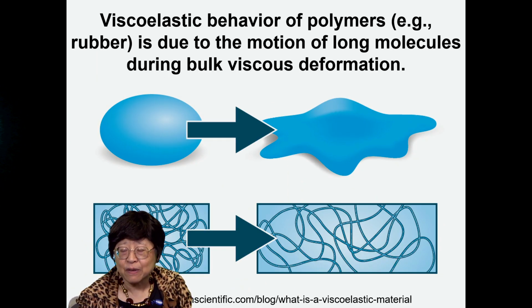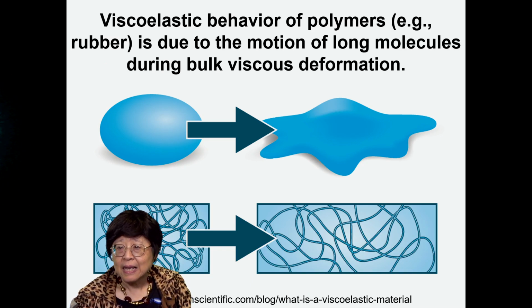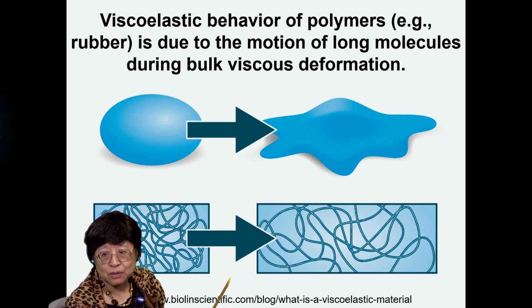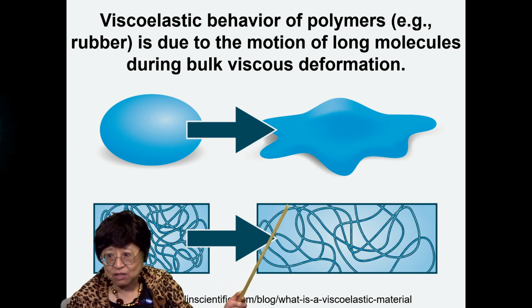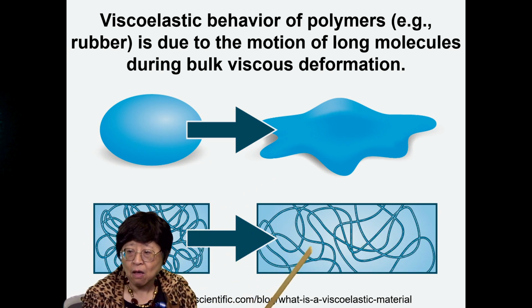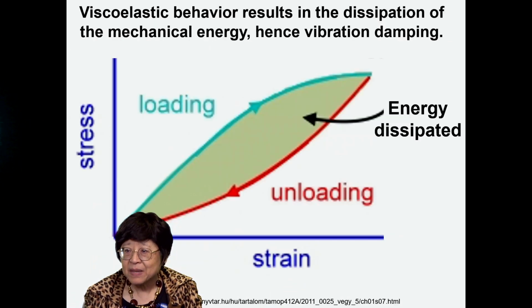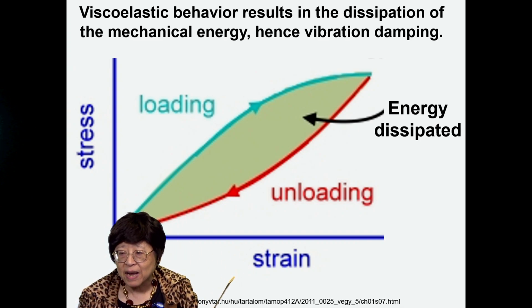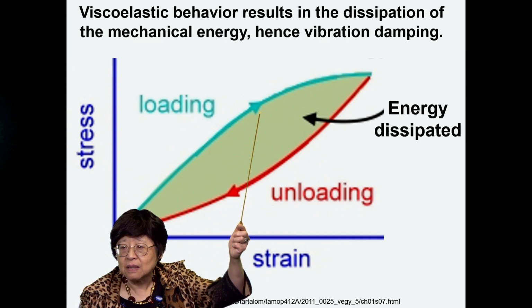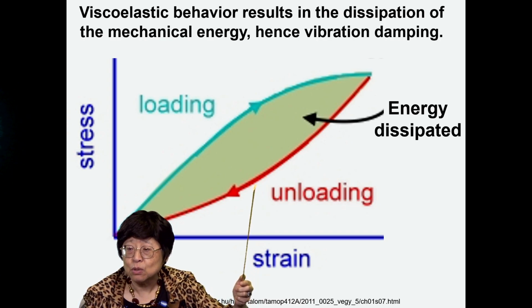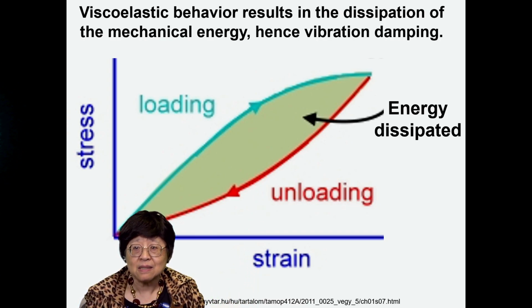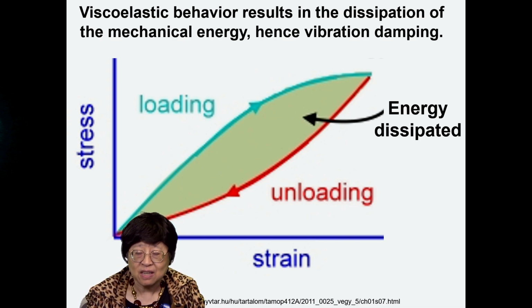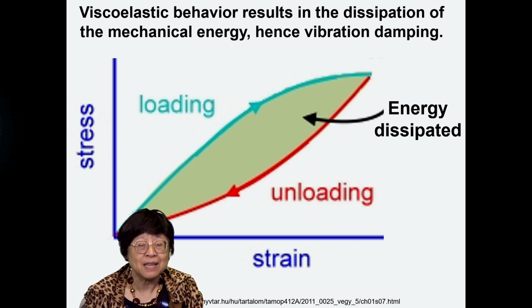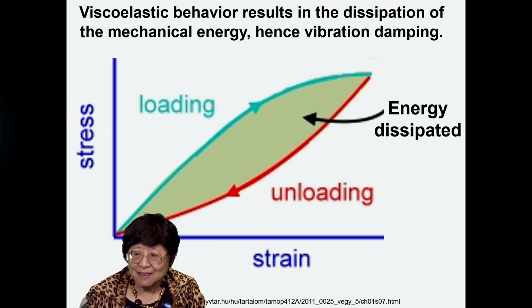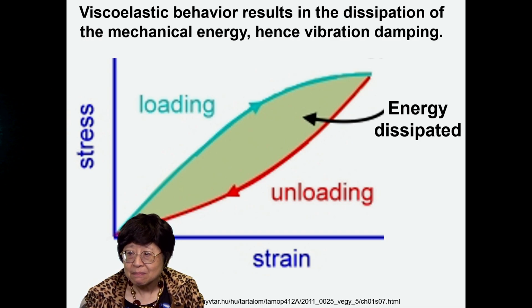And this behavior, in case of polymers such as rubber, is due to the motion of the long molecules inside during the viscous deformation. You just squish it, and then the long molecules move around, and that movement consumes mechanical energy. And this is the stress versus strain curve. During loading and then subsequent unloading, the two curves don't overlap. That hysteresis area relates to how much energy is dissipated, that is, how much mechanical energy is killed. And that is vibration damping.